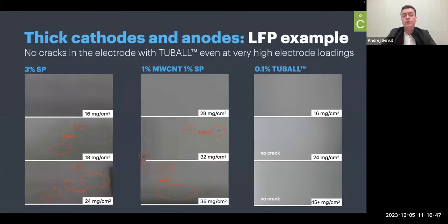And the same if we speak about cathodes. In this case, this is the result in LFP cathodes. We tried to maximize the thickness of the cathode, one-side loading, till the stage when we started to observe cracks on the surface of the electrode. To the left, this is carbon black group. In the middle, this is multi-wall carbon nanotubes group. And to the right, this is TUBALL group. So with Super P, we started to observe cracks at about 18 milligram per square centimeter one-side loading. With multi-wall carbon nanotubes, we started to observe cracks at 32 milligram per square centimeter loading. With TUBALL, 45 plus milligrams per square centimeter, no cracks.